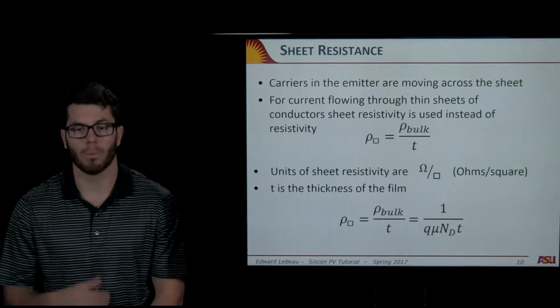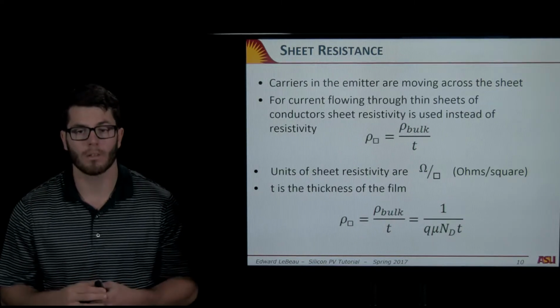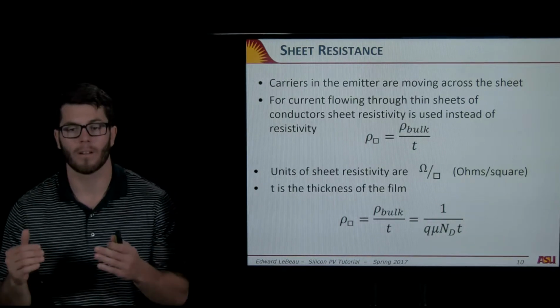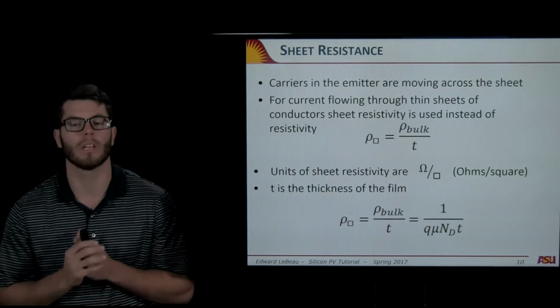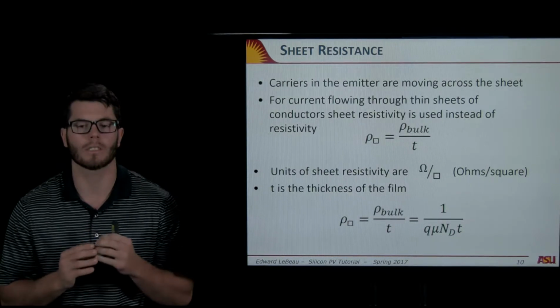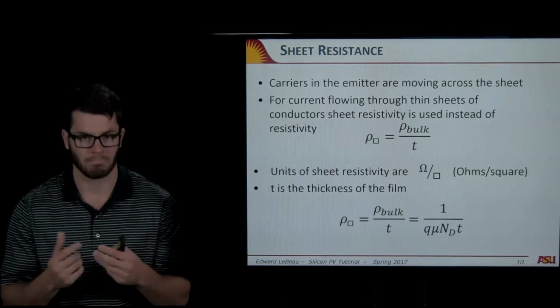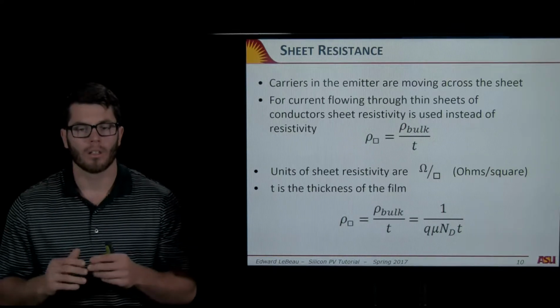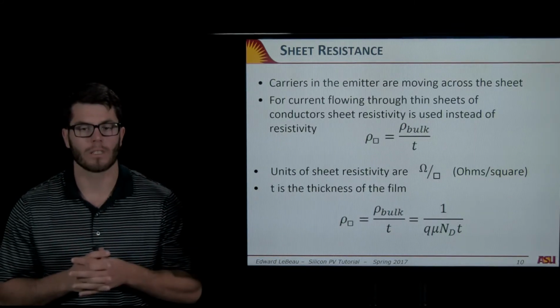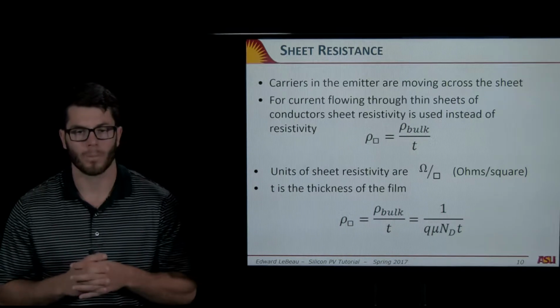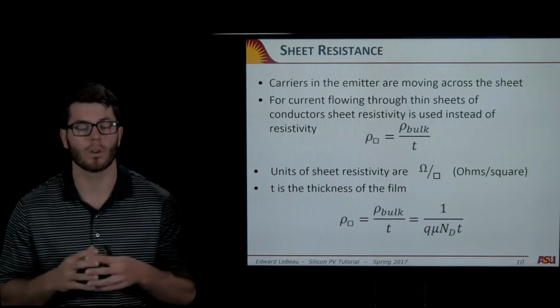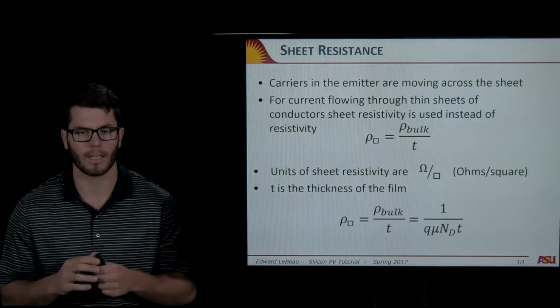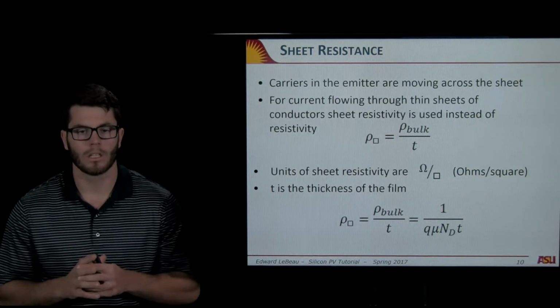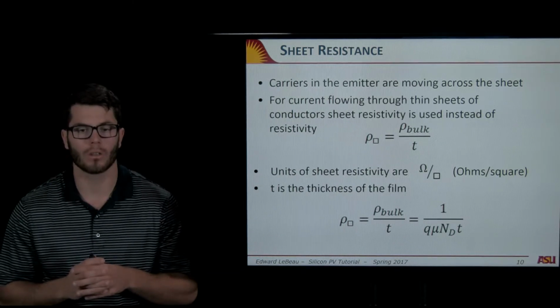Well, it's the resistivity of your bulk, which is basically a volume resistivity, or ohm-meters. If you want to think of that a little more clearly, it's your resistivity for an area. It's a little complicated. So basically your sheet resistivity is your resistivity of a square, ohms per square, which is your bulk resistivity over your thickness. And another way to look at that, and you see in that bottom equation, to the far right, 1 over q mu Nd t. So q is your charge, mu is your mobility, Nd is your doping density, and t is your thickness.